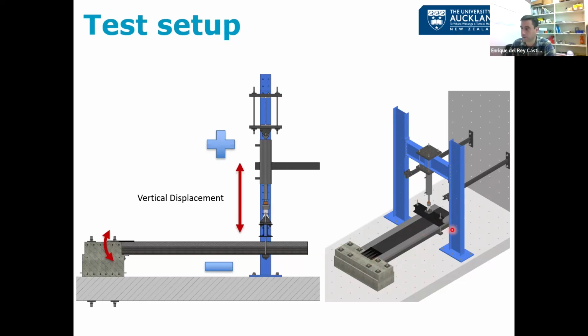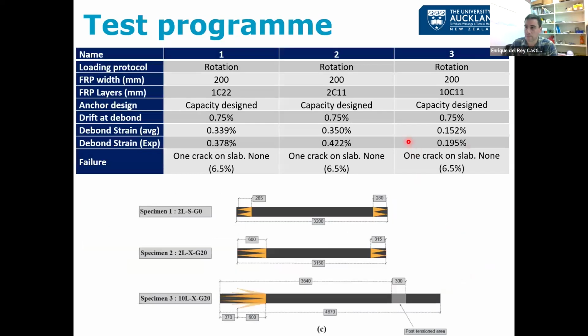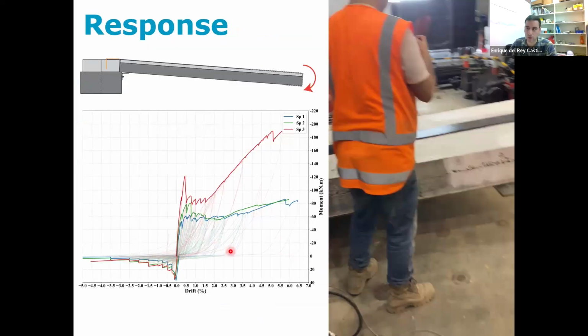Now I'm going to go briefly over the 7 tests that we have already done. So we change the thickness from 1 layer all the way to 10 layers. And we saw a very predictable response. The debond strain was a little bit higher than what we were expecting. So from 34 to 38, from 35 to 42. But the response is very similar to the single tie test. We have a very stiff elastic response, then the debonding, and then the anchor picks up.